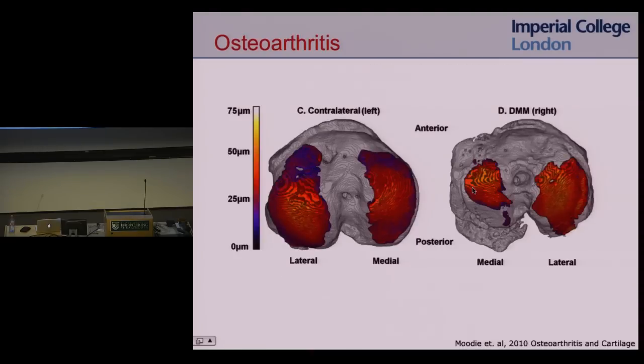Now, if we overlay the cartilage results on top, so this is the confocal scanning laser microscopy, we can get a three-dimensional image of what the cartilage looks like on the mouse knees. On the healthy leg, we see nice thick cartilage, so the thickness map, nice thick cartilage across the entire tibial plateau. On the arthritic leg, not surprisingly, where there's no bone, we also get no cartilage. So there's gaping holes in the posterior part, which makes sense. That's where we would predict the femur would be because of the change in mechanics. So most of the damage is in the posterior part.